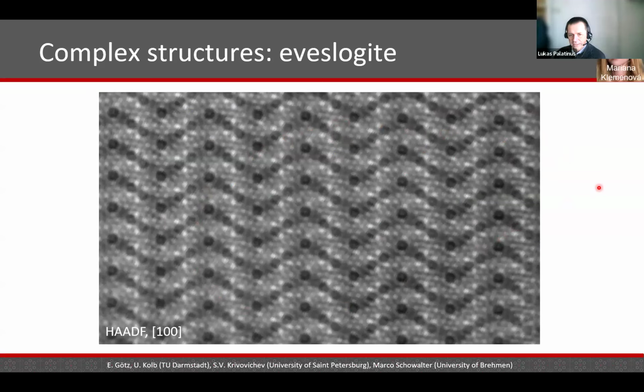visible in this image. And second, of course, it's hard to see immediately now for you, but when we overlaid the structure over the electron microscope images, it turned out that the match is perfect. So every single dot in this high resolution image corresponds to one cation in the structure determination that we performed. So that was very satisfactory, of course, and it's also a nice reminder that electron microscopy is more than just diffraction. Even for crystallography, it's useful to keep in mind that electron microscopes can provide even direct images of the structure. They can provide spectroscopic information. So there's a wealth of information available together with the collection of the three-dimensional electron diffraction data.